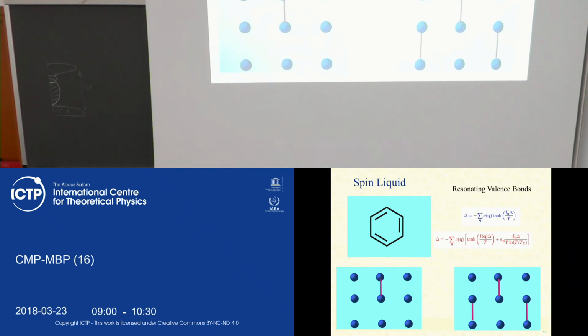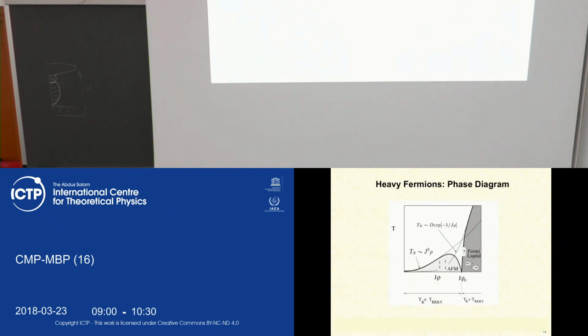However, if you magnetize your system, if you, for example, apply a magnetic field which freezes the direction of magnetization of the spin of the localized impurity, then you will not be able to flip it anymore. Therefore, a magnetic field destroys the Kondo effect. But on the other hand, if you have a molecular field associated with interaction between other spins, it plays the very same role as a magnetic field. So to say, the magnetization, so antiferromagnetic or ferromagnetic exchange, competes destructively with the Kondo effect, and in addition, some kind of spin-liquid correlations should be taken into account.